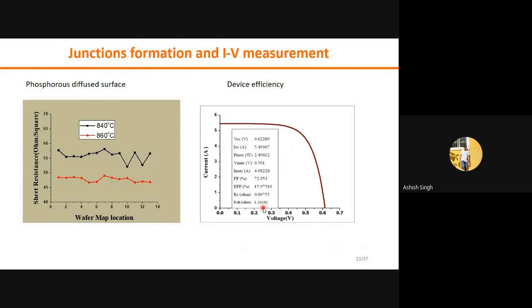Then the optimized textured wafer we moved to the tubular furnace for diffusion. This is a p-type wafer we were using. We use phosphorus trichloride or phosphorus pentachloride for the diffusion. With the diffusion we make the n-type emitter on the wafer, and this is the sheet resistance of the wafer after the diffusion.